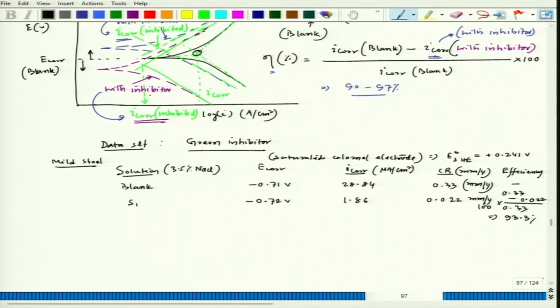So that means we could see that the efficiency is the corrosion rate without inhibitor minus corrosion rate with inhibitor, divided by corrosion rate without inhibitor. So this I corr, what I am talking about, we can also see this. If you use I corr, you should get the same values.